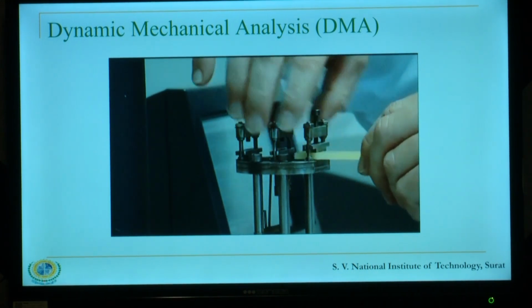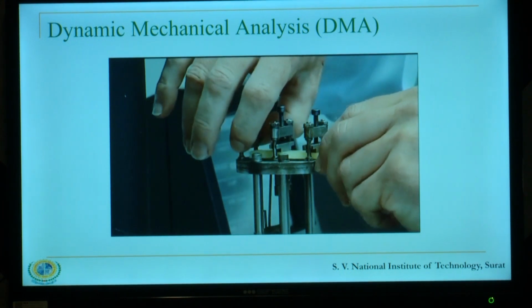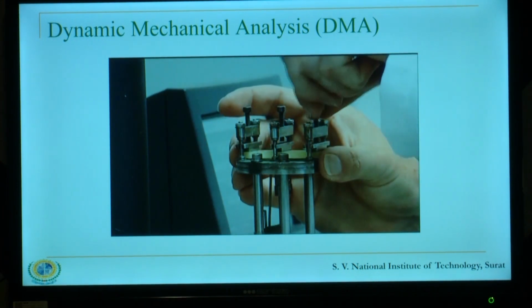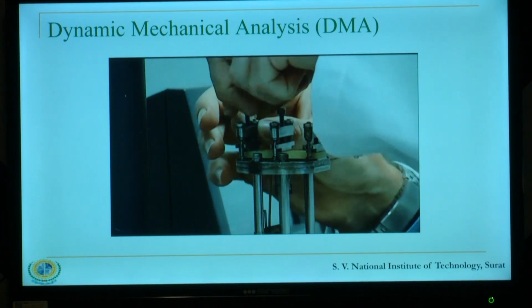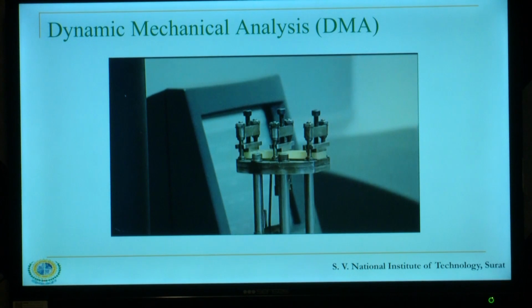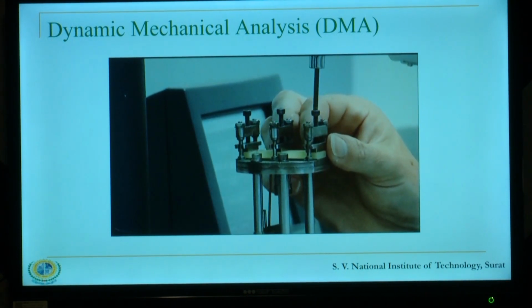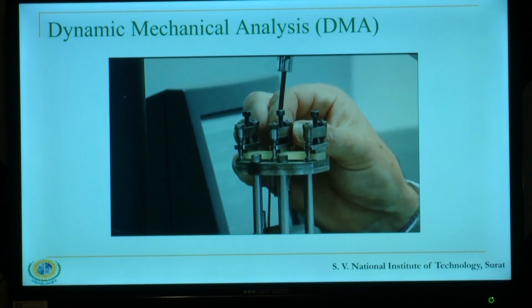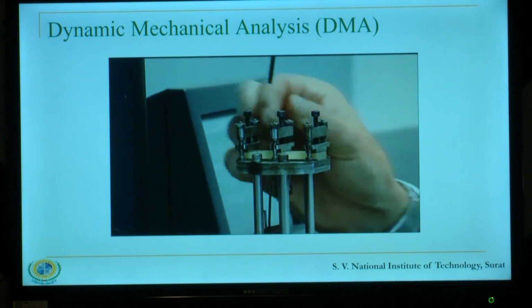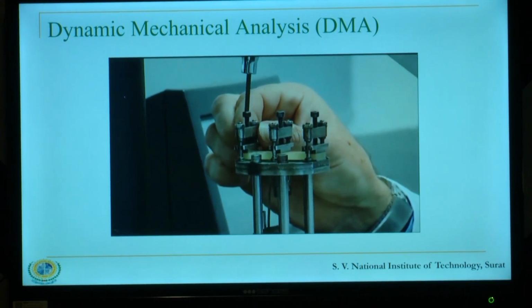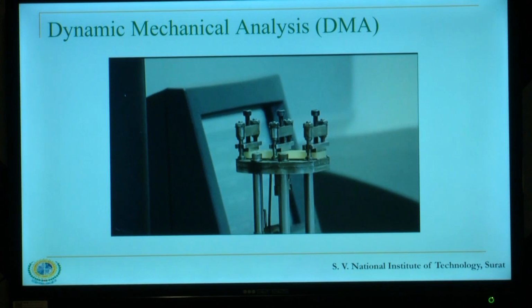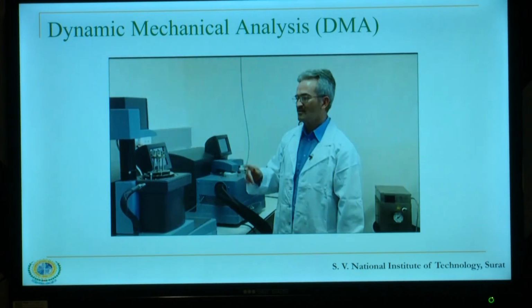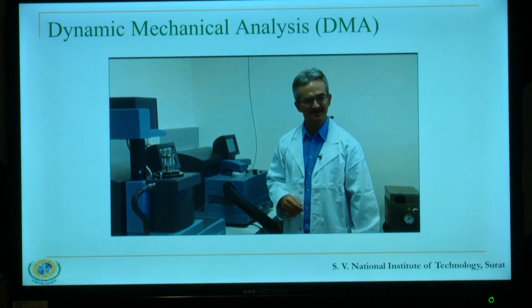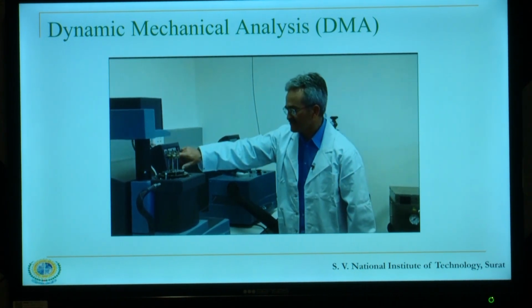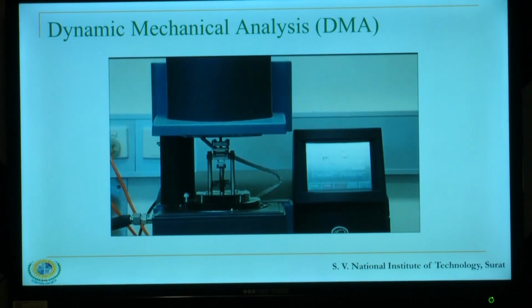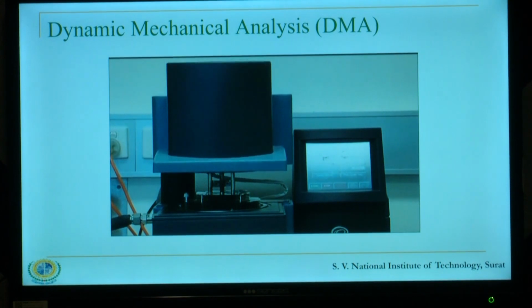Inside of the dual cantilever of the DMA instrument, we just put the sample inside and tighten the screws of the dual cantilever in this fashion, and use this special screwdriver to tighten it up. You tighten until you hear the click, which indicates the right pressure on the sample inside of the dual cantilever. Once the sample is properly mounted in the dual cantilever of the DMA, we just close the furnace of the instrument and go ahead to the computer.